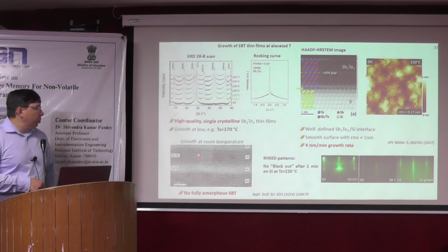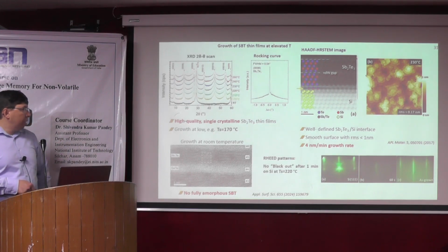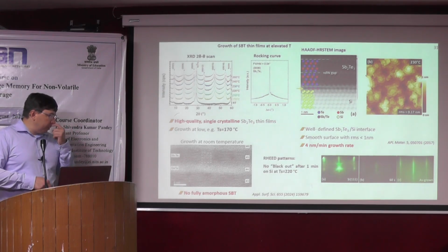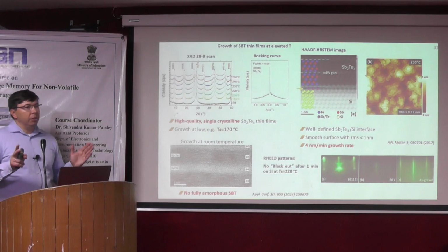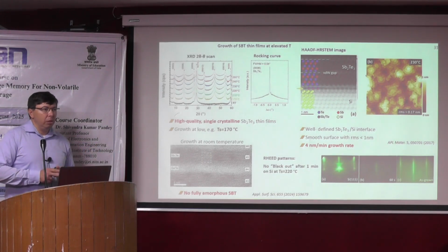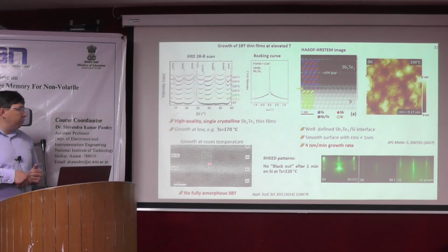Yeah, if you use room temperature growth, we did some thin films in this direction. It always remains crystalline, so I call it polycrystalline with some domains. Here in this publication we showed that we can reduce the thickness from 5 nanometers down to 3 nanometers, but we still find some crystalline domains, crystalline and amorphous. So in our case we cannot stabilize the amorphous phase.